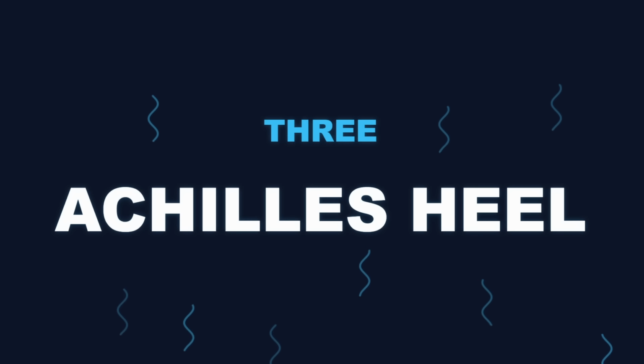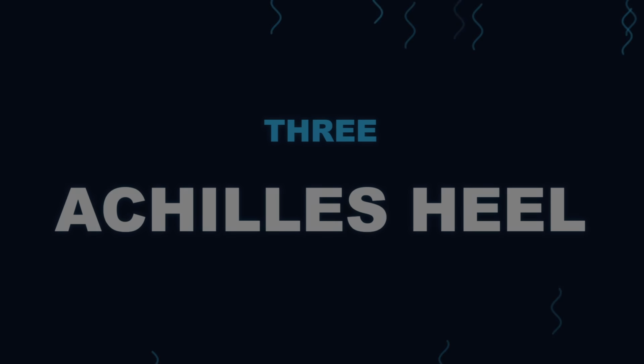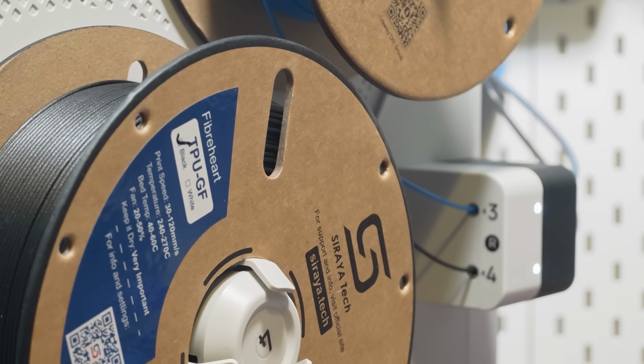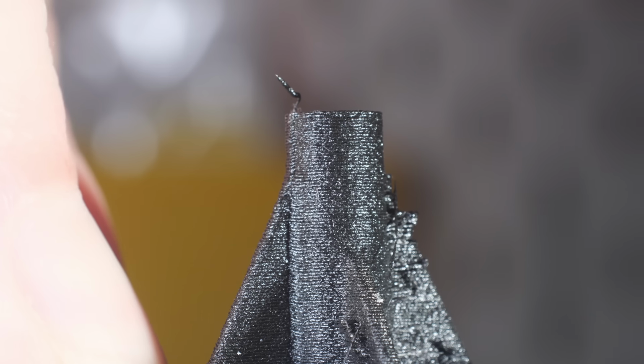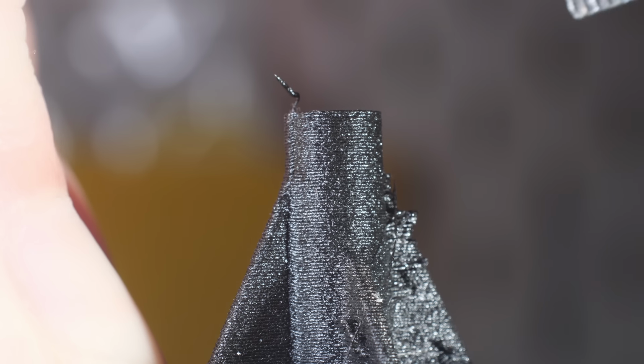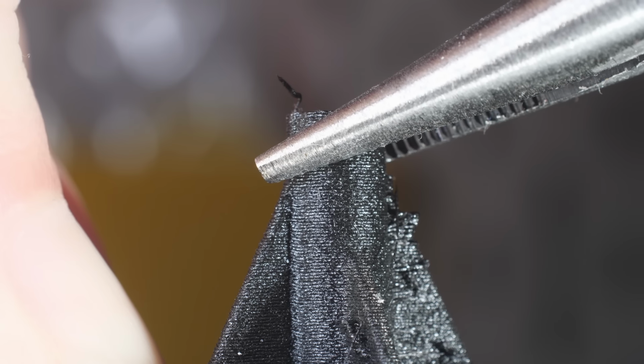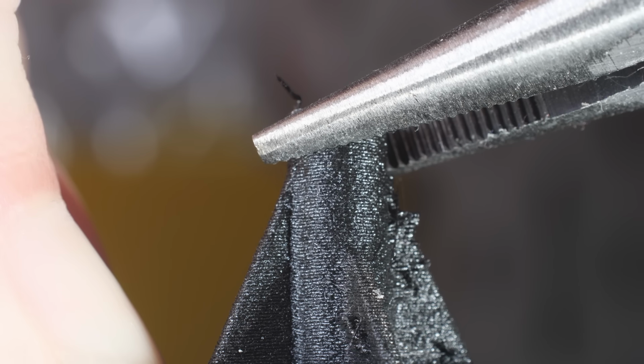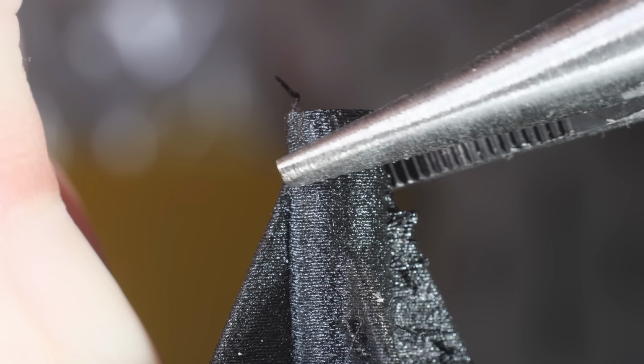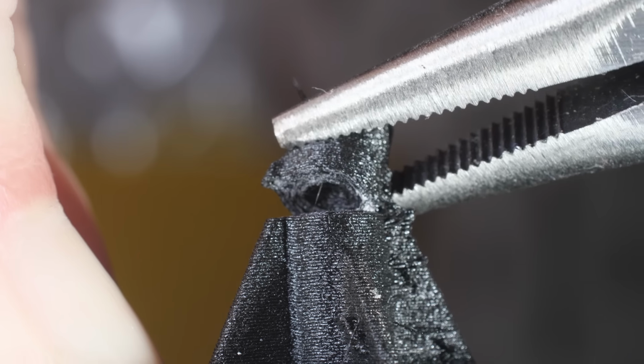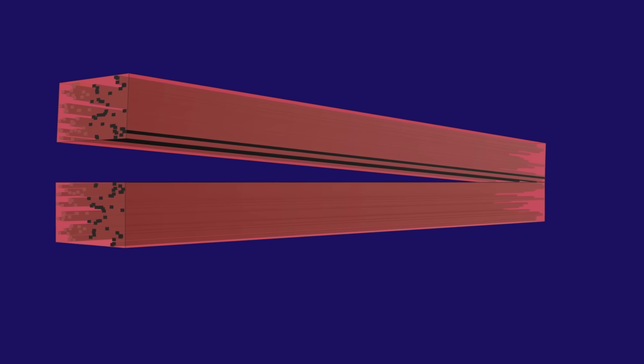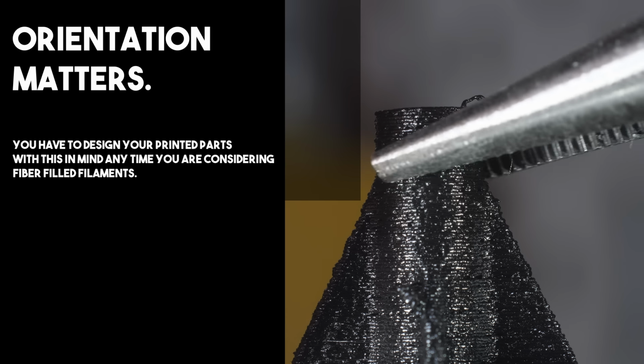As much as I'd like to tell you that this is the ultimate wonder material and you can't go wrong with it, you should print literally everything in it, that's actually not the case. TPU GF shares a weakness that all other glass fiber filaments have. In fact, some of them have it worse than TPU GF, and that is layer bonding. The glass fibers introduce a material interface that disrupts layer adhesion, and the more glass you have, the weaker the interlayer bonding gets. Annealing might be something you immediately think of that might fix this, but actually no, that's probably going to exacerbate it for reasons beyond the scope of this video.